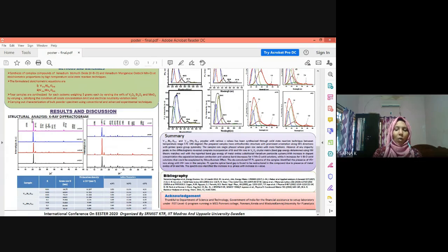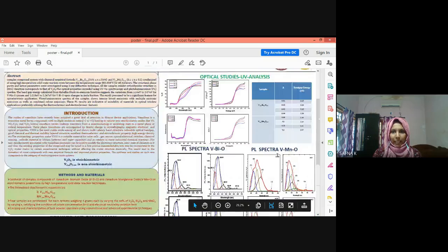The XRD peaks are analogous to pure V2O5 along different planes, and show a dominant peak at 2 theta equal to 20.54 degrees along the 001 direction. The patterns are high in intensity and sharp, which indicates improved crystalline quality of the samples. All the samples show the same phase and structure as pure V2O5, which can be indexed with an orthorhombic structure in the Pmmn space group. And this is the estimated grain size and lattice parameters. The obtained data shows insignificant variation in lattice parameters, suggesting the successful insertion of bismuth and manganese ions.